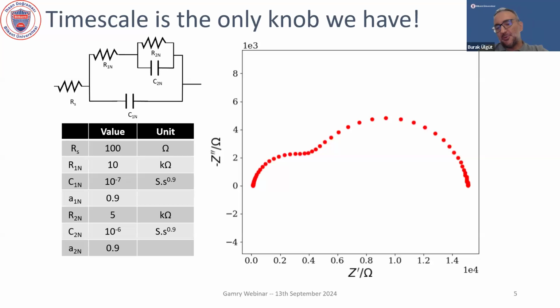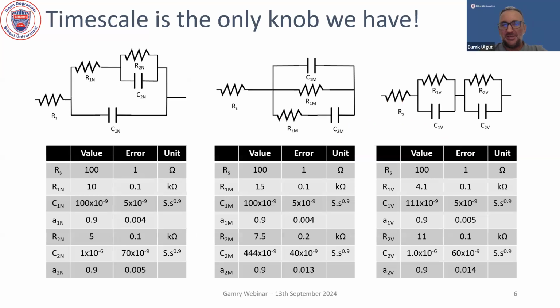And what I'm going to tell you now is that I don't have a single spectrum here. I actually have three spectra that are overlaid that can be calculated with all these different models. So the spectra of all of these three models, all with two time constants, for different R's and C's, all overlap. And this is analytical. This is not just coincidence. One can analytically show that the spectra for all three are identical.